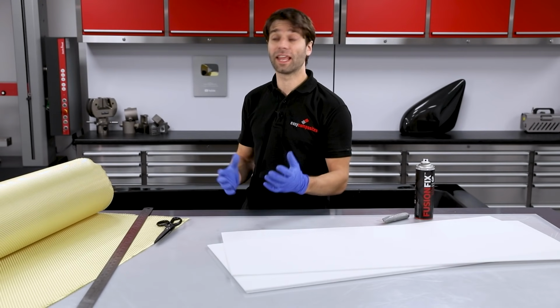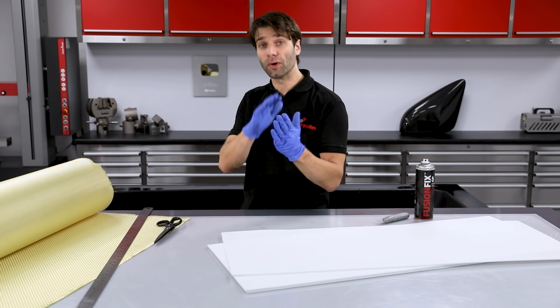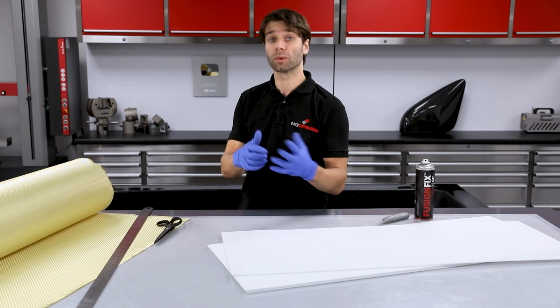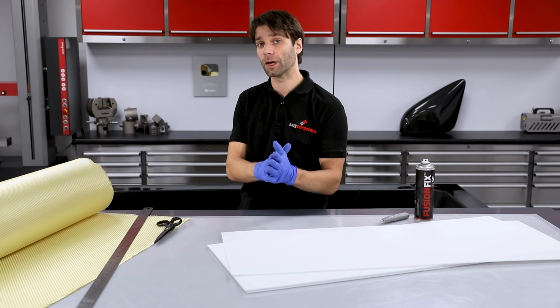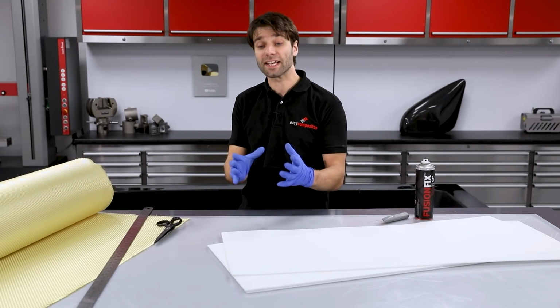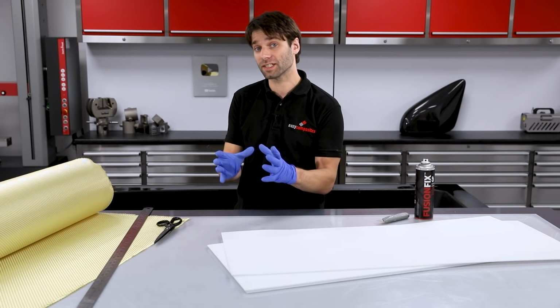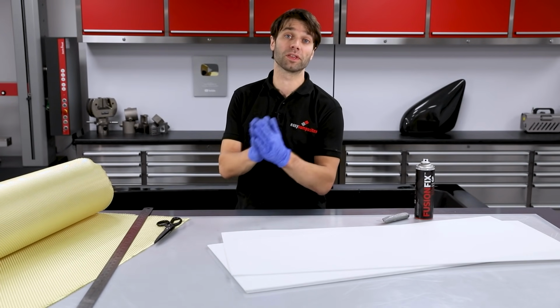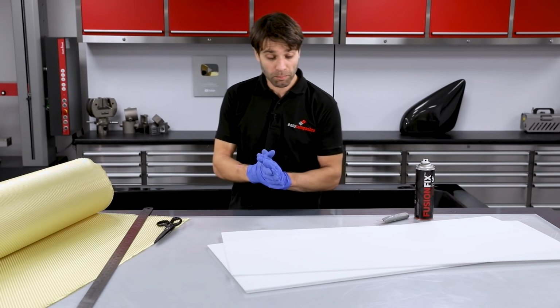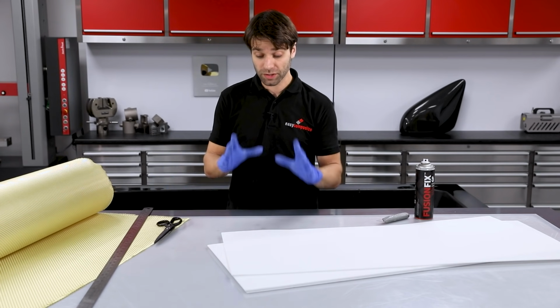The gel coat has now been left to fully cure. Now when it does cure, it cures without any surface tack at all, which is unlike a conventional polyester gel coat. This is part of its function and allows the epoxy resin backing to fully bond to the surface. I will stress that if you were to use a conventional polyester gel coat, you can't back that up with an epoxy resin. So if we move on now to the materials themselves, we're going to start by looking at